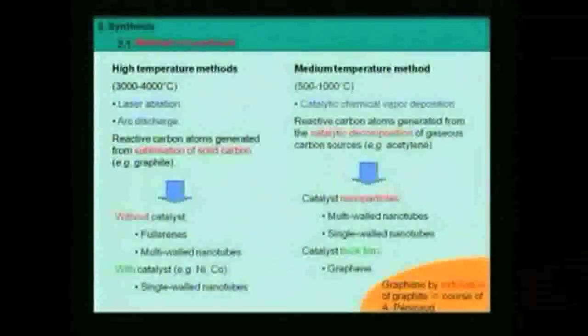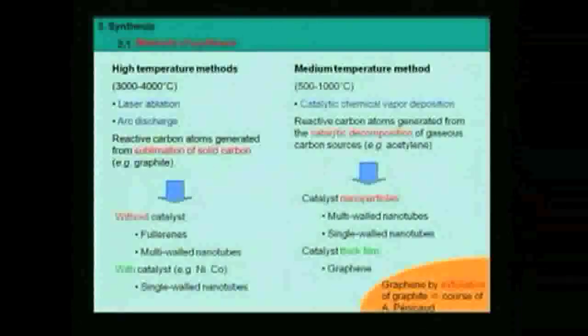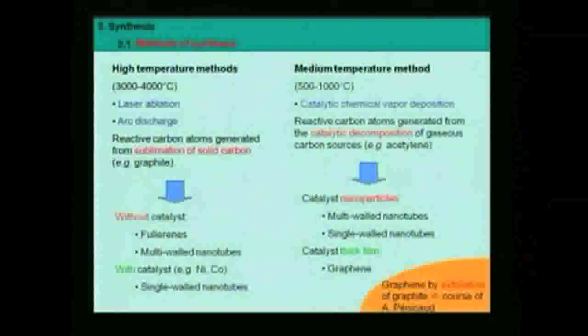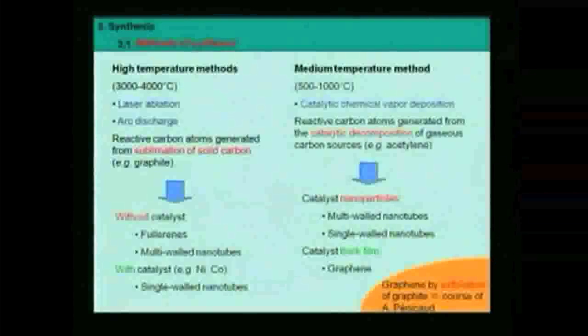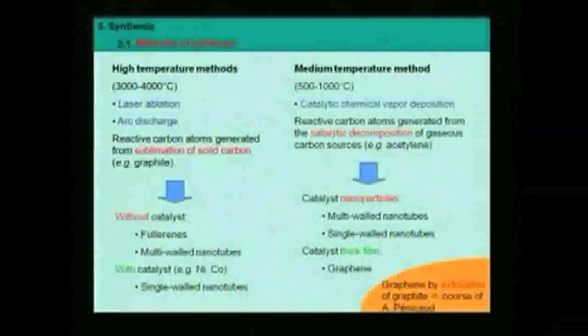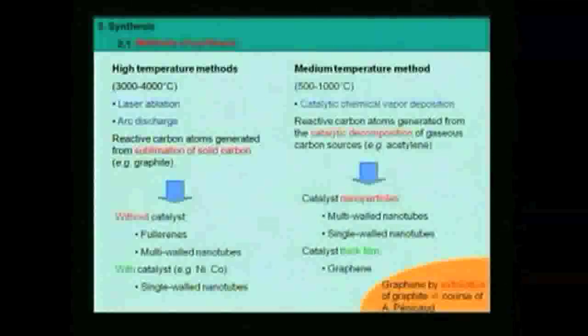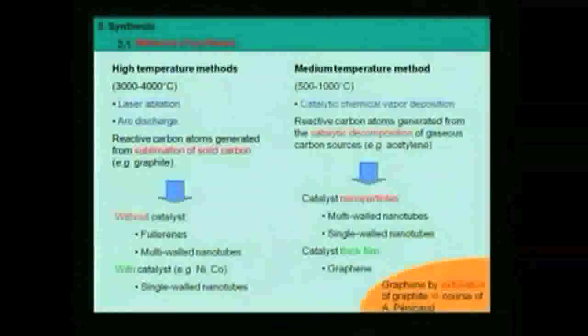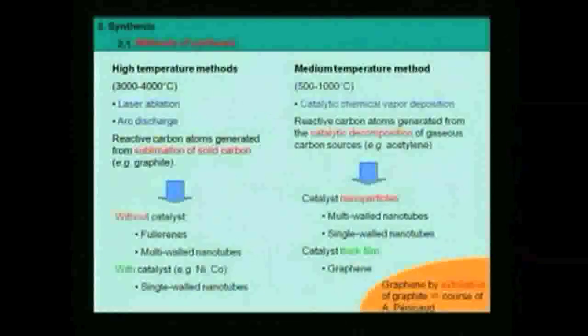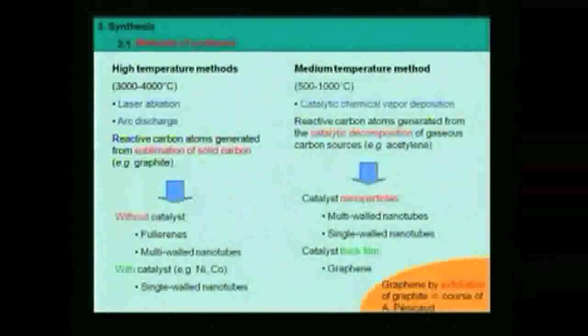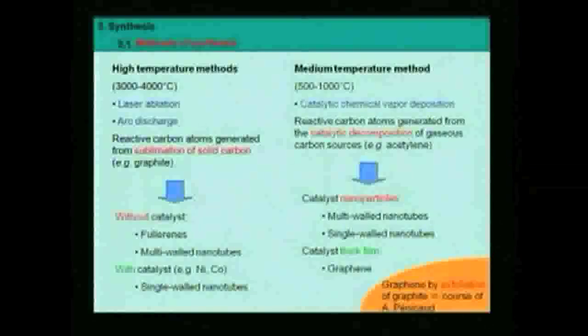Okay, it's important also to mention that presently graphene can be quite easily obtained not by these high temperature techniques, but by using a natural material, which is graphite, and to exfoliate graphite, it means taking each plane of graphene out of graphite one by one. There are different techniques to do that, especially in liquid suspension of graphite, and this will be discussed and presented in detail during the course of Alain Pénicaud next week. So I will not talk about this important technique of preparation. This is not synthesis, but it is important that you know about this method of preparation of graphene, because it allows to make a lot of material and at a low cost.